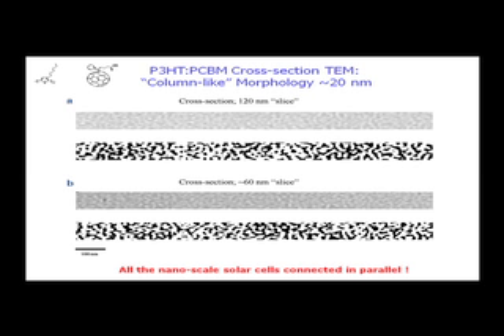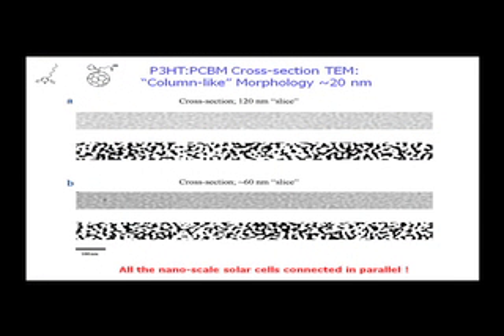Okay. So this is a bulk heterojunction material. This is 100 nanometers thick, or in this case 60. And you tend to form, in this case fortunately, a morphology which is column-like. Right here, there's a heterojunction. Right here, there's a heterojunction. This one's particularly nice. You see a continuous pathway all the way across. That's a solar cell right there. That heterojunction forms a solar cell. Here's another one. Here's another one. It looks like that one doesn't connect to the electrodes, but I don't believe that. I think if I took the next slice and the next slice, I would find that this thing wanders up and connects to the electrode, and almost all of them do.